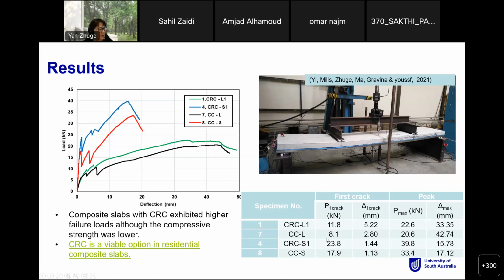So these are some results you see for the CRC L1, maximum stress is up to about 22. The cracking stress was higher than normal concrete, and the ultimate strength is also higher. For the short spans, the cracking load was much higher, and the ultimate load is also much higher, increasing from 33 to 39. For this testing, we repeated each test with about 6 slabs and got very consistent results. So although the compressive strength reduced, we have improved flexural performance of the composite slab.